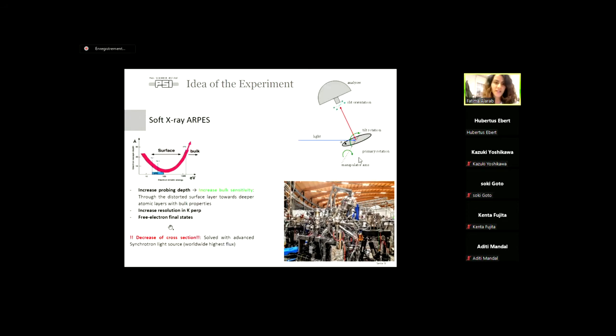Also, soft X-ray is very important because it's better than the UV because we increase, in this case, the resolution in k perpendicular. So then we can map the dispersion in three dimensions, not only in 2 dimensions. And yeah, only one bad thing about soft X-rays is that there will be a very important decrease in the cross section. All right, and this will decrease a lot the intensity of the photoelectrons.